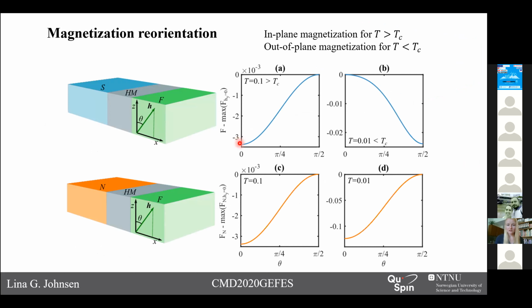As you see in panel A, the minimum of the free energy is for an in-plane magnetization direction. And in this panel, we have a temperature above the superconducting critical temperature. If we decrease the temperature below the critical temperature, as we have done in panel B, we see that the minimum of the free energy shifts to an out-of-plane magnetization direction. So what we see is that we have a reorientation of the magnetization from in-plane to out-of-plane.